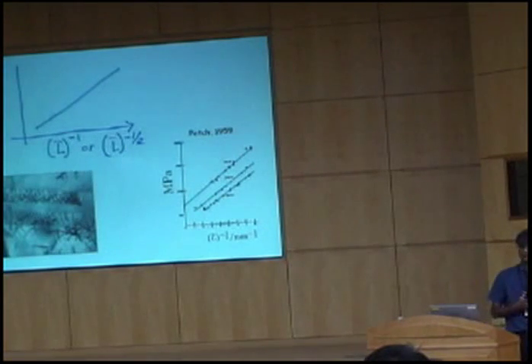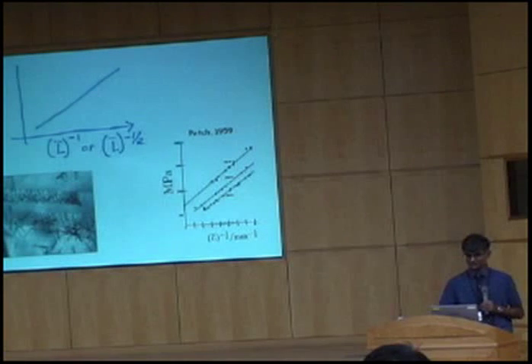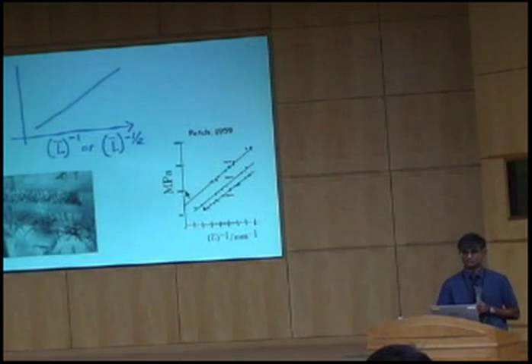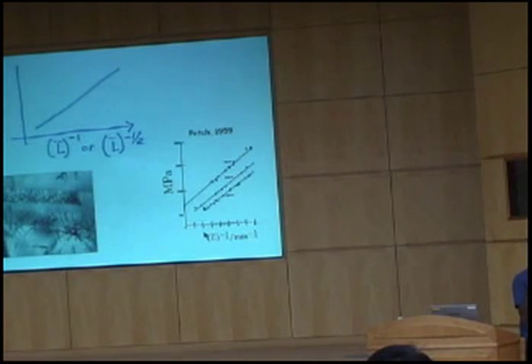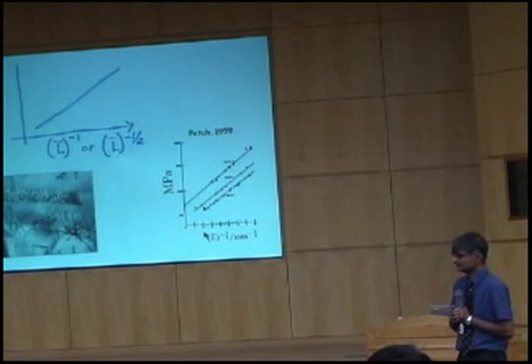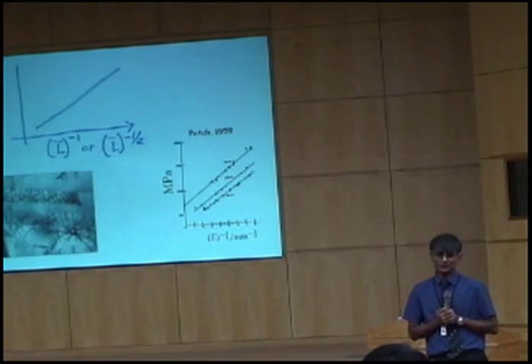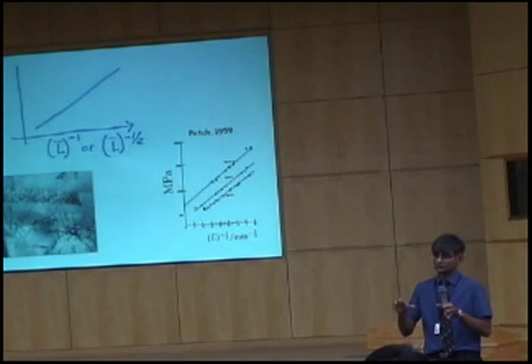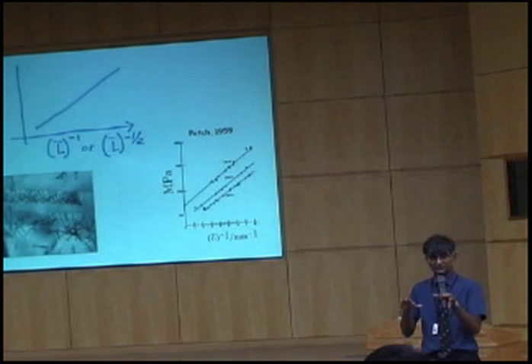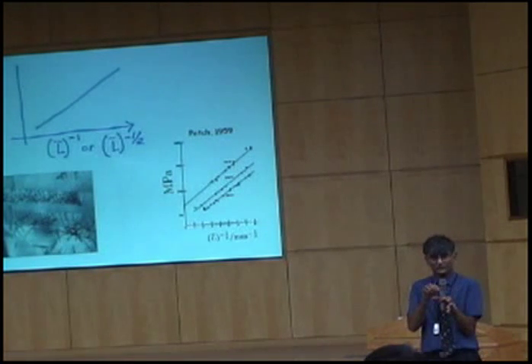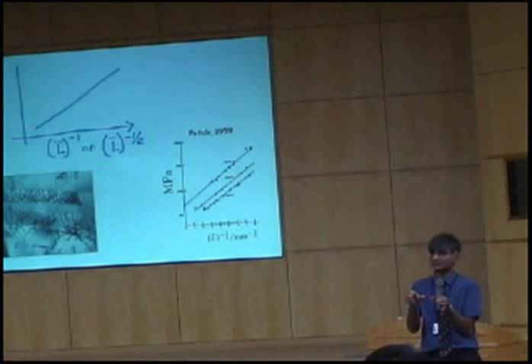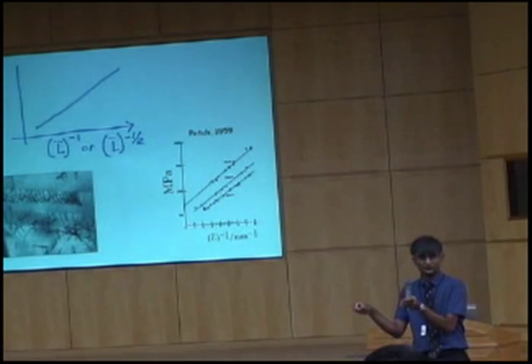Now, the normal way of looking at grain size strengthening is the Hall-Petch equation here, where we plot the strength as a function of 1 over the grain size to the power of a half, 1 over the square root of grain size. And the Hall-Petch equation comes from the propagation of slip between two different grains. So you have slip starting in one grain, it forms a barrier of dislocations at the boundary, and that triggers a dislocation source in an adjacent grain.